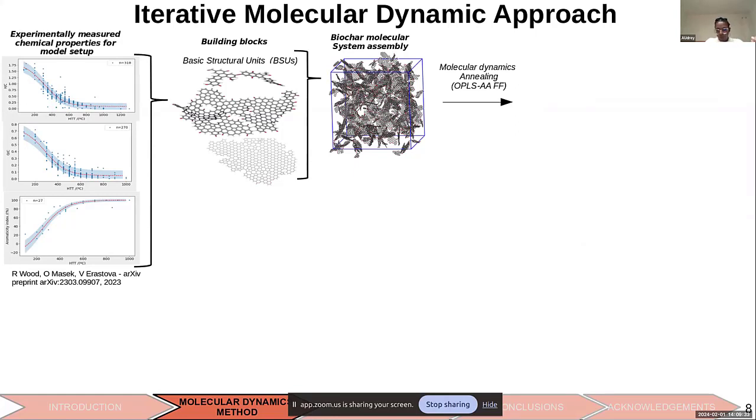the OPLS force field, which describes the interaction between the different building blocks, and the way they're going to arrange themselves is determined by that force field. We use the Lennard-Jones potentials, which is a 12-6 potential, for how they interact, the non-bonded interactions between these building blocks.